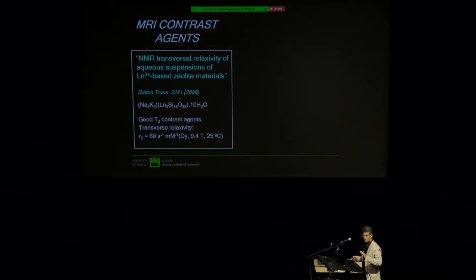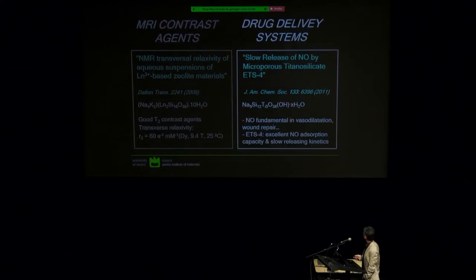We have also used these materials in other applications, for example, in MRI as MRI contrast agents. I think this was a paper in common with Eva. I'm not sure if this was the right one, but we basically evaluated the possibility of using suspensions of these lanthanide-bearing materials as contrast agents, and we found that they are good T2 contrast agents, not good T1 contrast agents.